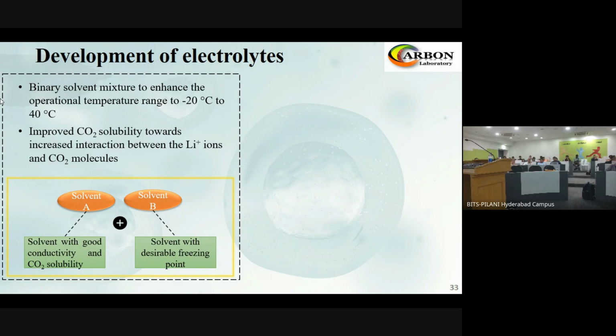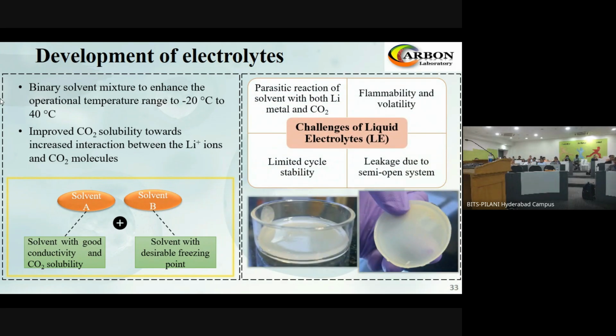We are also looking into the different liquid electrolyte challenges, because ultimately when we want to go for safer batteries, solid electrolyte is the way forward. Parasitic reactions of solvent with both lithium and CO2 are one of the reasons we want to switch towards solid electrolytes. Then there are flammability, volatility of the liquid electrolytes, and leakage, and it's more because it's a semi-open system, unlike the closed system of other batteries like metal ion or metal sulfur. It's a semi-open system. One side is porous, so we really have to look into solid electrolytes to avoid the leakage, and limited cycle stability. That's again another area.